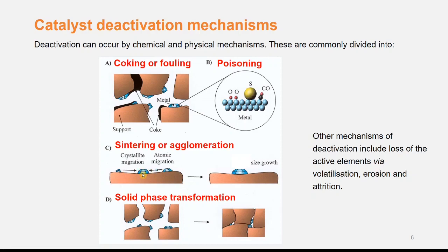On the other hand, if you have high temperature, atoms are more active, meaning they vibrate more, so more chances for migration. So here, we can see that smaller crystals of catalyst join together to form larger ones. What do you think happens to the total surface area? The total surface area reduces, so there are fewer active sites available to catalyze the reaction.